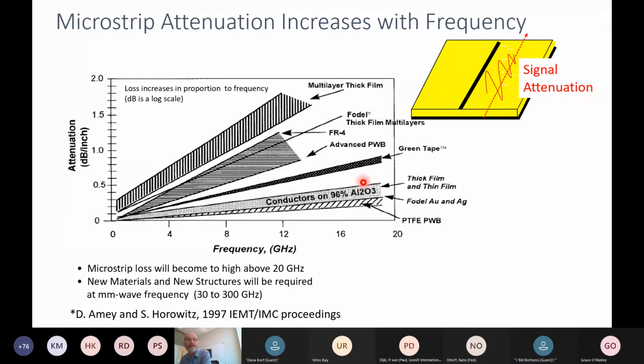So you can see that there's a variety of attenuation lines depending on the dielectric, and also, which is not really captured here, for a 50 ohm impedance you actually have a different conductor geometry as well, which also contributes to this. But basically, as we increase frequency, we definitely get an increase in this attenuation per unit length.